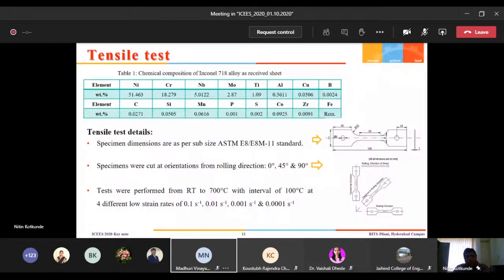You can see that from room temperature to 700 degrees means 8 different temperatures, 4 strain rates. So 8 into 4, 32 tests in one particular direction. So 32 into 3, we have tested the material and repeated it thrice. So almost more than 300 tensile test experiments we have conducted on the Inconel material.